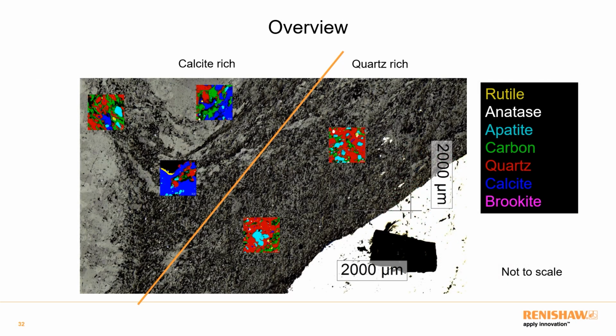Combining all those images, just as an overview, I need to point out these aren't to scale, just to give you an idea of what the composition is so we can draw some general conclusions. What we can see is the bulk of the sample is primarily made of calcite. You can see that with these blue regions. If we go to the black layer, we can see it's primarily quartz and carbon, with slightly increased levels of apatite, although I should point out apatite is generally present everywhere anyway. But this lets us basically understand what we've got going on here. So the bulk tends to be calcite rich. The dissolution region tends to be quartz rich, and so that's our conclusion.